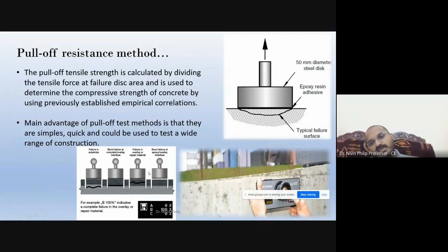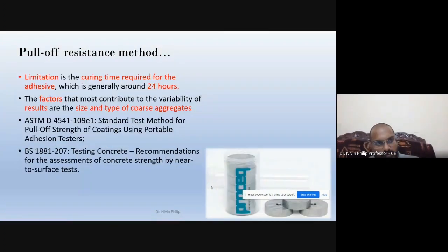Then we pull out, the crack will happen, and we find out how much bond strength there is. When designing, we will see some bond strength value, which is based on the shear stress of the concrete. That shear stress value we get from the test. These have some limitations: we need 24 hours for setting the adhesive, and the result is also influenced by the size and type of coarse aggregate. Because we are using a 50 mm dia disc, a 20 mm coarse aggregate has some limit. Otherwise, we have to increase the size of the disc.